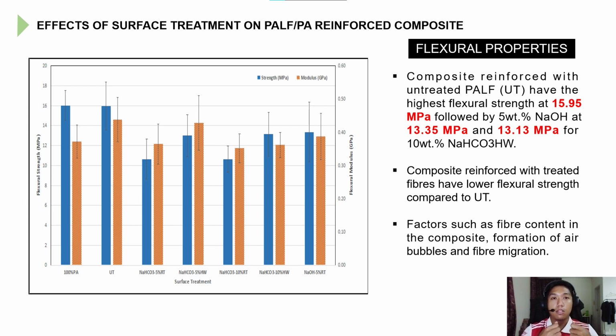And also I observed that the air bubbles in the composite are also the cause of the result itself, since the flexural bending could be affected by these air bubbles in the composite.